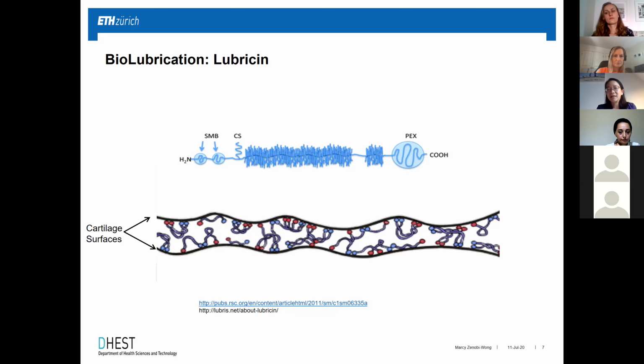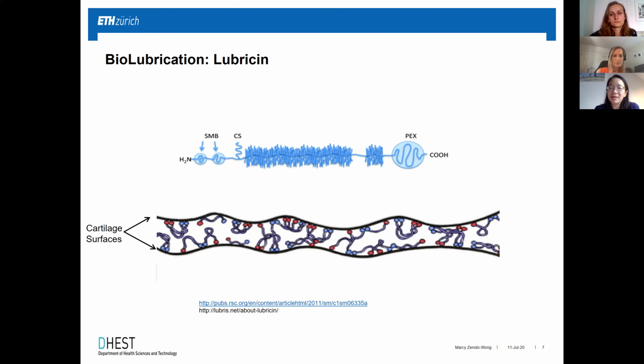And there are many people that have studied the physics of how this biolubrication starts. It's a complicated situation, but it's been found that there's a molecule that is expressed by the cells right at the surface. This molecule is called lubricin, and it binds in a non-covalent manner to the surface of cartilage. And because it has this brush-like hydrated middle domain, it renders the surface very slippery. So what you see here is just a cartoon imagination of how lubricin would be attaching to this cartilage surface. It binds and unbinds. You can shear it away and it reforms.